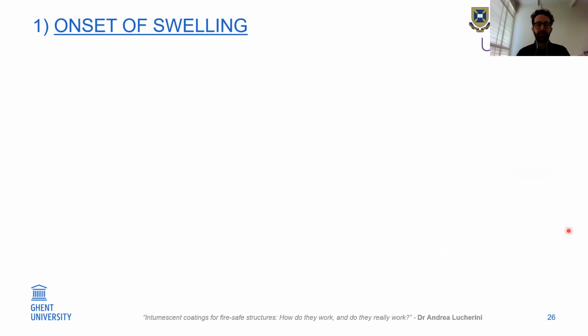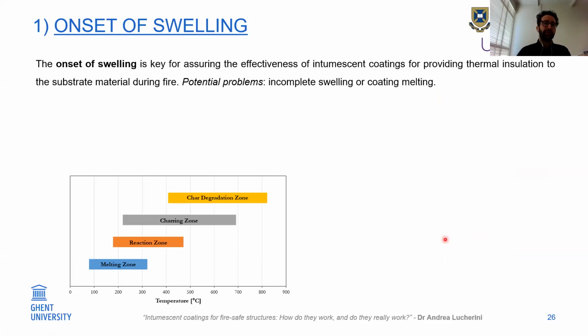The first aspect is the onset of swelling. What I mentioned earlier is that the Intumescent process usually happens with different zones or different processes: the melting zone, the reaction zone, the charring zone, and the char degradation zone. What is key for Intumescent coating is the swelling, in particular the onset of swelling. So I asked myself, what are the conditions that promote the onset of swelling? The onset of swelling would be defined as the end of the melting zone and the beginning of the reaction zone.